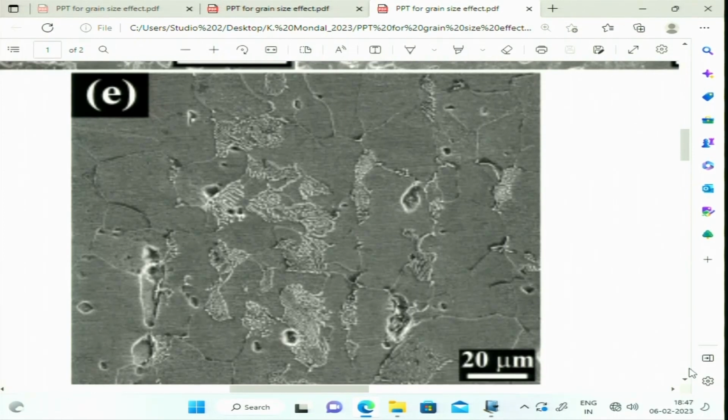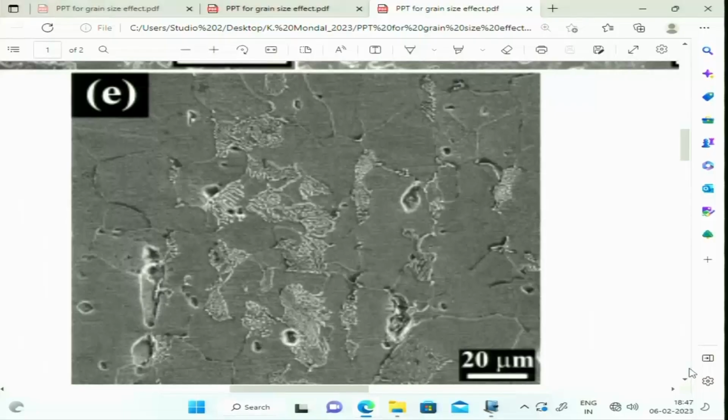Now, if we polish the top surface, that is a light polish on a cloth, and then take it to SEM, in fact you will start seeing the grain features. These grain features you can obtain by etching, and when you do etching, as in nital, you can clearly see those grains and pearlite, but here etching was not used. Just after polarization we have taken it to the SEM. So, that means it must have got etched due to the electrochemical process during polarization. So, there we could see a nice grain pattern as well as pearlite.